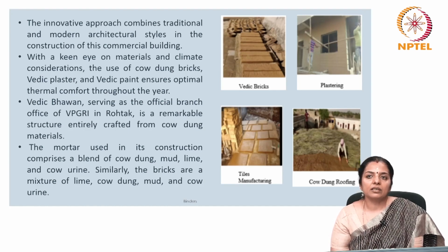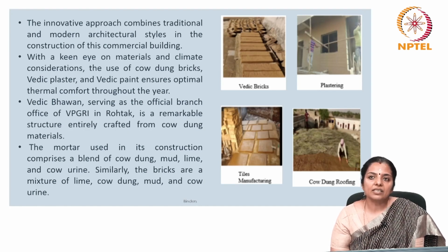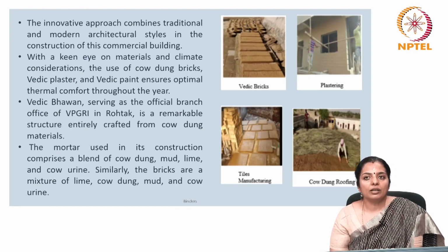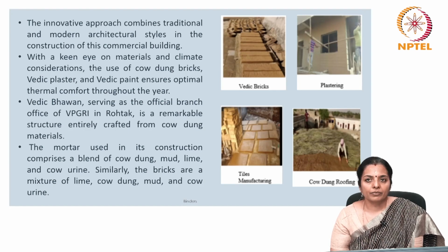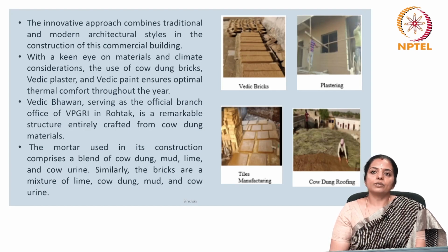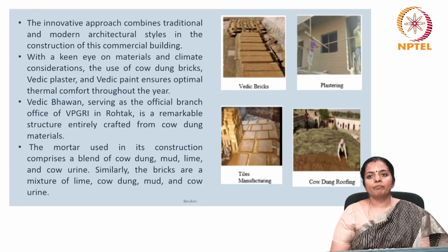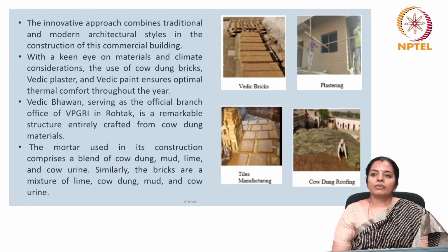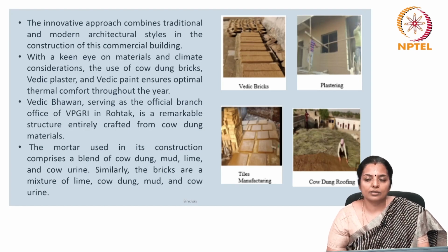The Vedic Bhavan, serving as the official branch office of VPGRI in Rohtak, is a remarkable structure entirely crafted from cow dung materials. The mortar used in this construction comprises a blend of cow dung, mud, lime and cow urine. Similarly, the bricks are a mixture of lime, cow dung, mud and cow urine. Vedic plaster is a powerful composition of 60 to 70% gypsum, 20 to 30% cow dung, 8 to 9% mud and 1% citric acid, which adorns the walls.